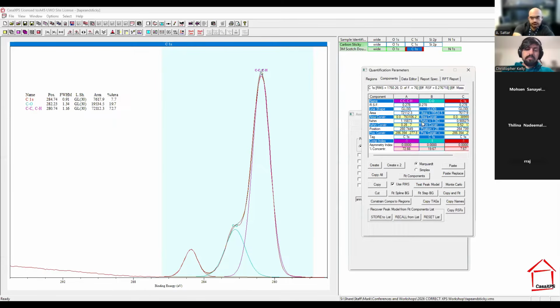And we can go in and change the constraints of this peak to be the same as peak 1, or peak A. You can see now they both have the same full width half max. And if we refit, it seems to clean up the fitting a little bit. And it looks like we're getting a pretty good approximation of what's going on here on this sample.